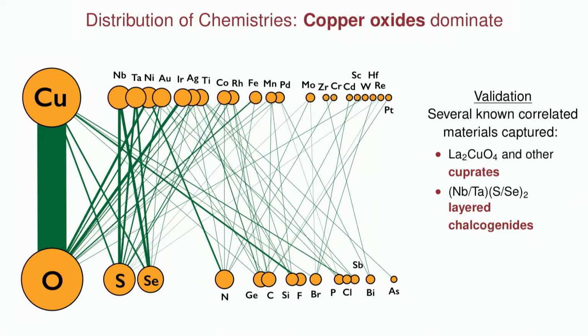So we can also look at the particular chemical bonding in terms of this network plot in which the size of the nodes and the edges is proportional to the number of compounds we find. The main thing you can see here is that copper oxides really, really dominate. It seems to be the most prevalent way to achieve this screening. Maybe not so surprising given that those cuprates are copper oxides. We also see a good number of sulfides and selenides. And you do see that there is a good amount of chemical diversity in terms of the overall number of metals and anions that we do find.